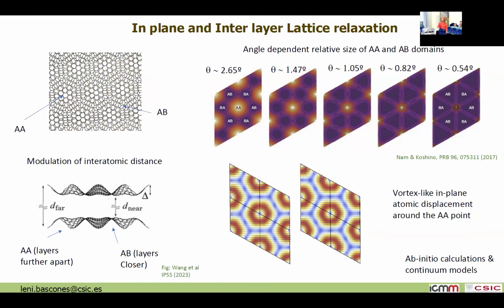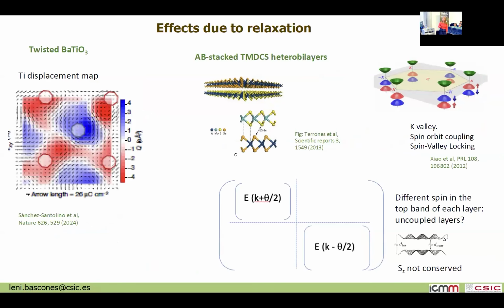This has been calculated in different ways, both with ab initio calculations and through some continuum models for the elastic energy. Okay, so you can see, for example, the displacement map of the titanium in this twisted bilayer. What you see here is also the way in which it moves. There are these vortices.